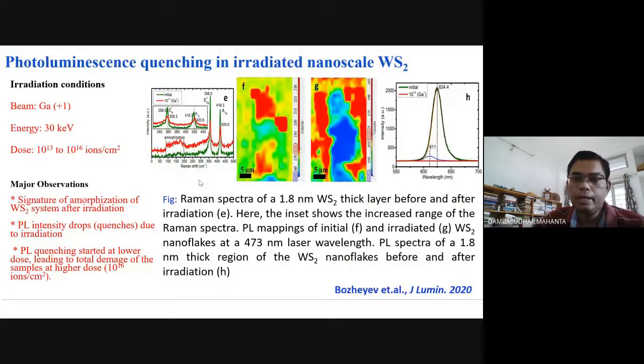Now similarly, in another work, in nanoscale WS2, photoluminescence quenching was found beyond a critical fluence. So the left hand side is Raman spectra. You know, in case of WS2, you have two modes. One is E2g1, which is in plane mode, and another is A1g mode, which is out of plane mode. And if you have exfoliated sample, if you are going from a stack of layers to a few layers, in that case, this particular peak is going to be suppressed as compared to A1, which is out of plane one. Okay. So when you have exfoliated layers, this peak is going to be dominant over this.